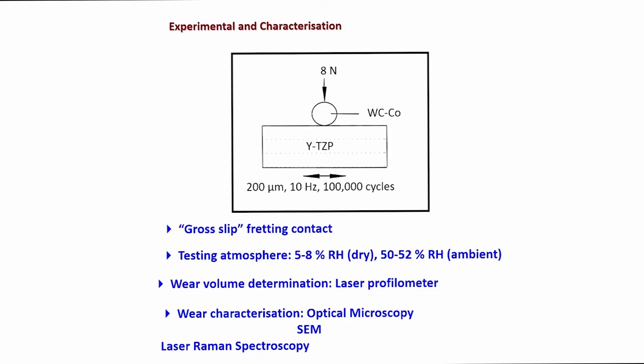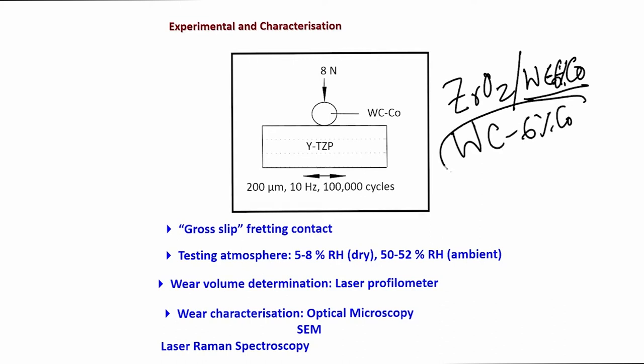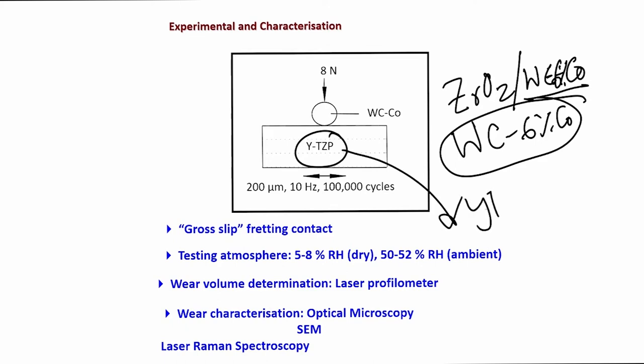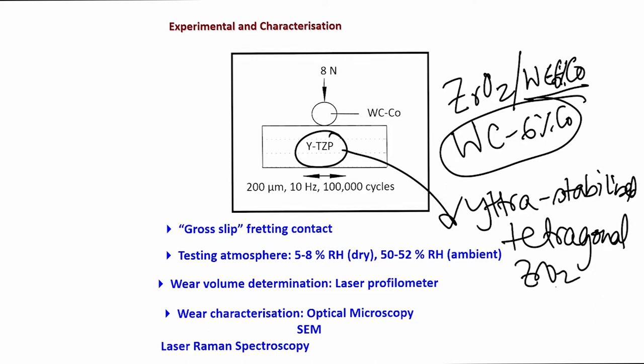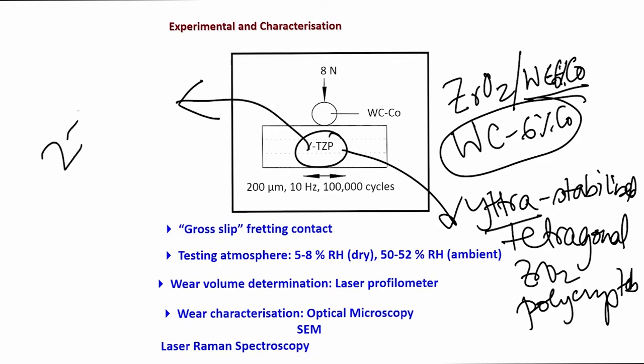So we have not only used zirconia in one of our studies against transformation toughened zirconia, so that is called self mated, zirconia versus zirconia. But in this particular case we use zirconia versus tungsten carbide cobalt, which is a hard metal. And here this cobalt percentage is 6%. So tungsten carbide 6% cobalt, that is a typical hard metal that we have used. Now this YTZP stands for yttria stabilized tetragonal zirconia polycrystals. What it means is that you add yttria, so essentially this zirconia is yttria stabilized, yttria doped zirconia. The amount of yttria here is typically varied between 2 to 3 mole percent, okay.